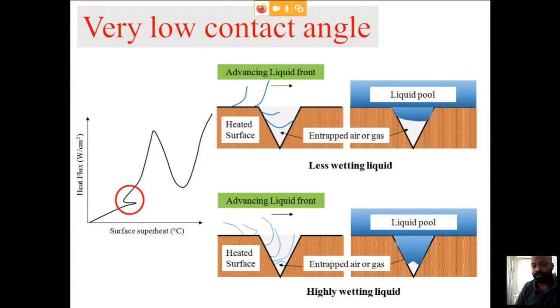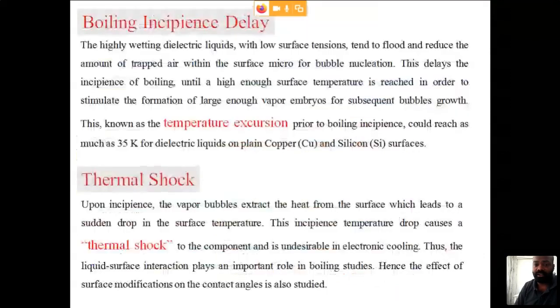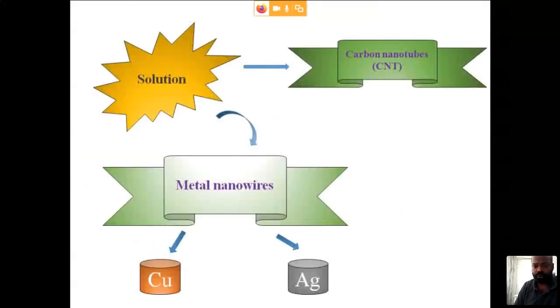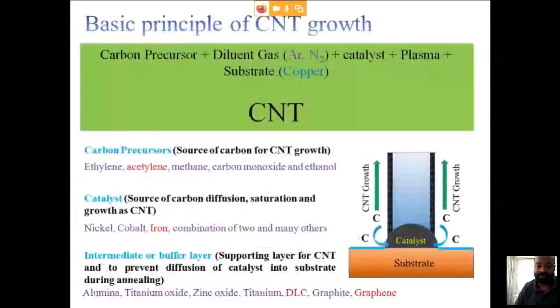There is no vapor actually, because this FC72 is highly wetting in nature. It's highly wetting because surface tension is very low. So that's why this will completely flood whatever available cavities are there. So you have to give some extra provision for the nucleation, and that's where the solution comes as metal nanowires and carbon nanotubes. So we have given some surface coating which will give you some extra nucleation sites.